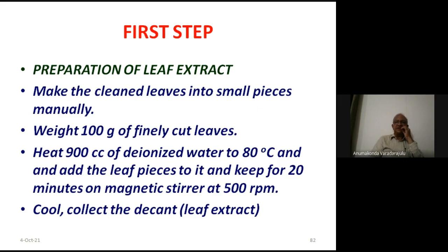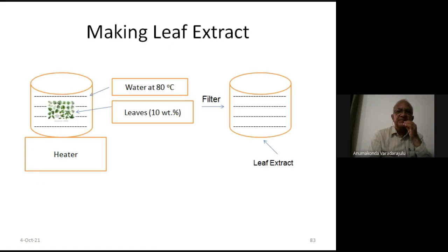So you'll be getting the extract of these chemicals into the water, and we call it a leaf extract. This is illustrated here. This is the water at 80 degrees, and then these leaves were added here, 10% leaves, and we allow it to stand for 20 minutes and then filter, and this is the leaf extract. So in the first step, we made the leaf extract and then allow it to cool and keep it in a refrigerator until it is used.